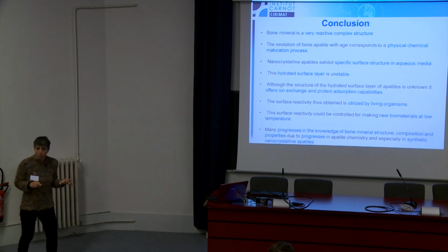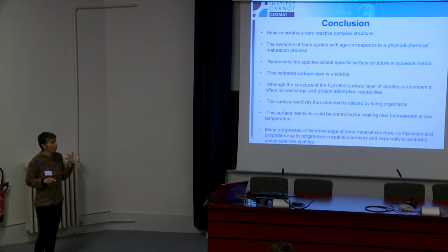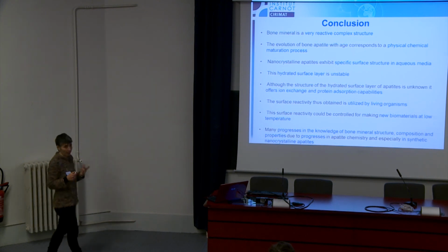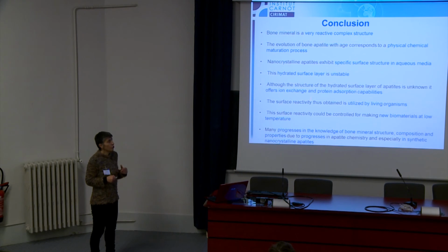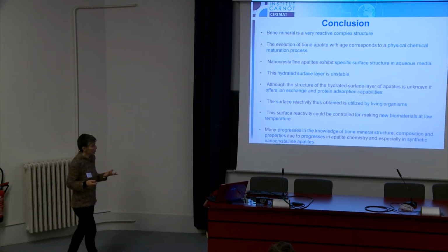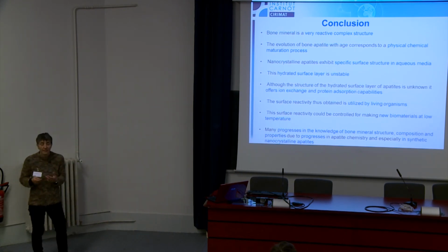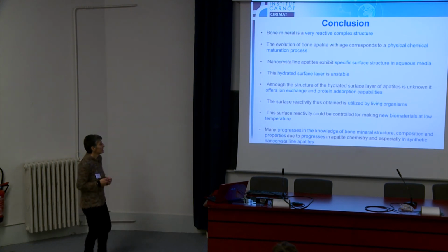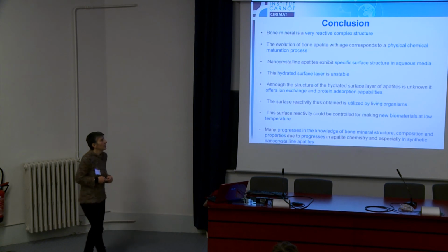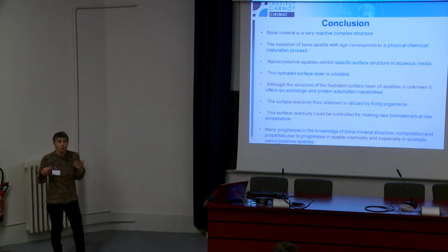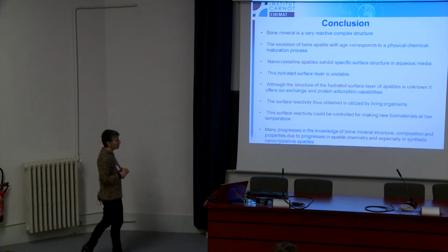This hydrated layer structure offers ion exchange and protein adsorption capabilities for these crystals. And this surface reactivity can thus be utilized by living organisms. And also the surface reactivity can be controlled to prepare new biomaterials at low temperature.